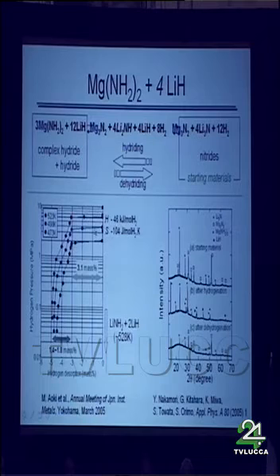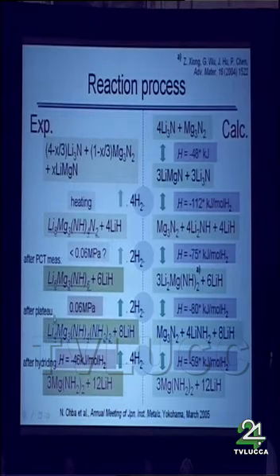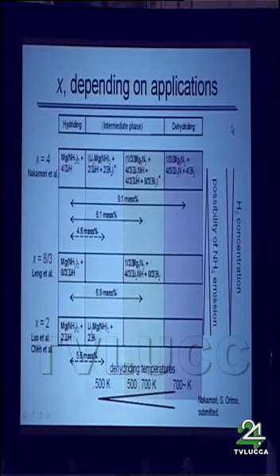We have measured the PCT properties on these samples, and we have also confirmed the reversibility just by heating this sample. Also, we did a precise study on each step of the dehydriding reaction of the combination of amide and hydride, experimentally and also theoretically. I can say that it's quite complicated, but what I'd like to propose here is that this composition ratio, this value of X, can be selected depending on the application condition. Which temperature we can heat up the sample, or how sensitive to the ammonia, or how much hydrogen we need also. Again, X is tunable from 2 up to 4, depending on the application condition.